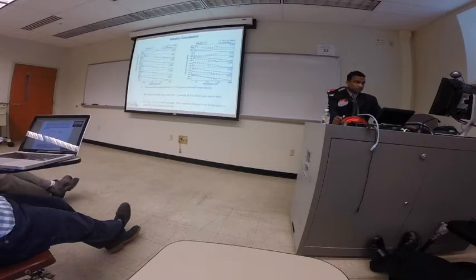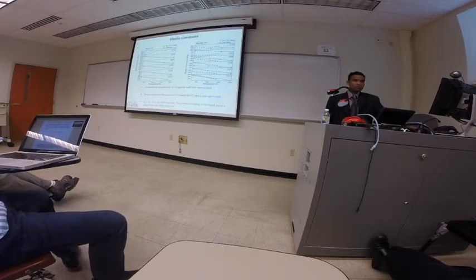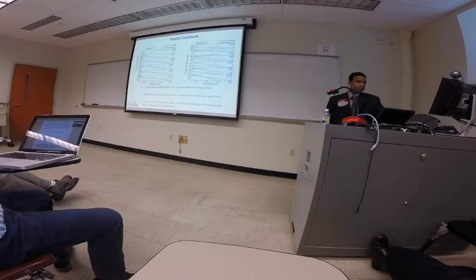Well, that was experimental work, Ito et al. Ito's work is the red dots, and those are experimental observations of the shear term for this crystal. But for the other ones, like C66, it's not too bad, it's just shifted a bit. And C33 slopes off a little bit, but the trend is right. C11 is, of course, beautiful. Also, you have to factor in the difficulty of measuring the full elastic tensor of a crystal.